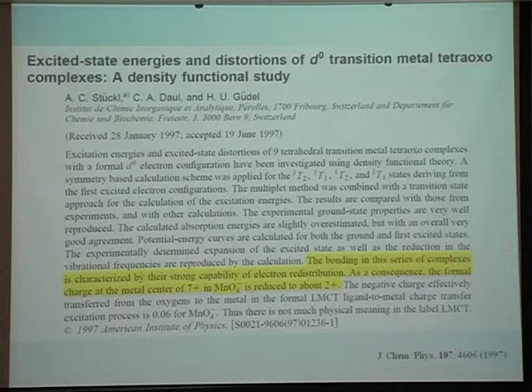complexes, here the complex is the MnO4 minus permanganate complex, is characterized by a strong capability of electron redistribution. What's most shocking is that, as a consequence, the formal charge at the metal center of 7+ in MnO4 minus is reduced to about 2+. So the nominal Mn7+ O4, it seems manganese goes to Mn2+.